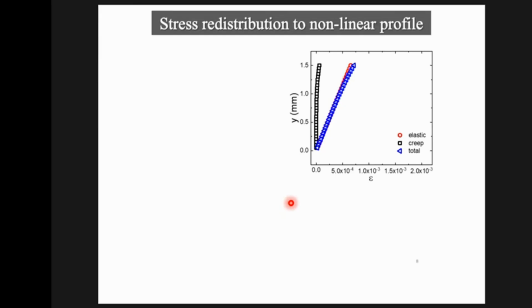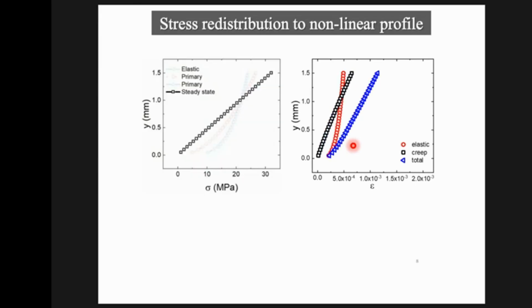So here's what's happening. The point 0 is the neutral axis, the midpoint of the beam. So we're just showing one half of it. And the x-axis is the strain. When you start, you're predominantly elastic, and so the total strain and the elastic strain are more or less the same. There's very little creep. Now, as you start creeping, the nonlinear part of the deformation becomes more and more important. And so your stress now has to adjust itself because the strain remains linear and therefore the stress can't be linear. So what you have is this phenomenon of load shedding. Namely, instead of the stress being here as in elasticity, it drops. And over here, near the neutral axis, it actually increases.